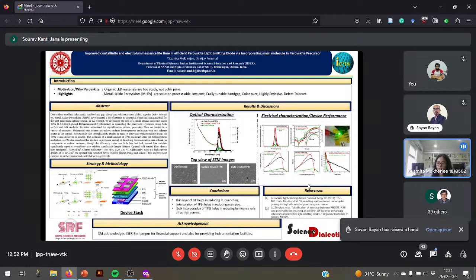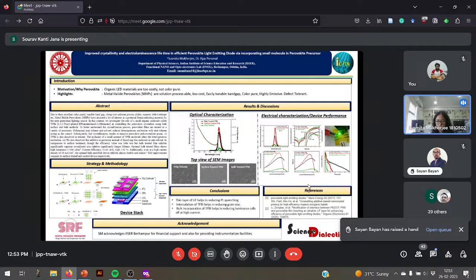In the conclusion, I would like to conclude that I use a thin layer of LiF between my HTL and my perovskite layer to protect against PL quenching. Perovskite is conducting and my HTL is also conducting. If two conducting surfaces touch each other, the exciton, the electron-hole pair, will be dissociated. To protect that, I use a thin layer of LiF, and TPBI intercalates between the grains and helps to minimize the grain size, and bulk incorporation of the TPBI helps in reducing the luminance roll-off at high current density. That is the main thing of my part.